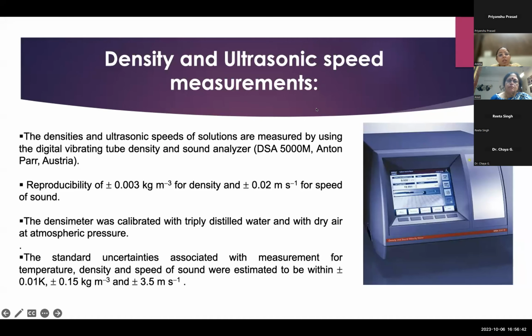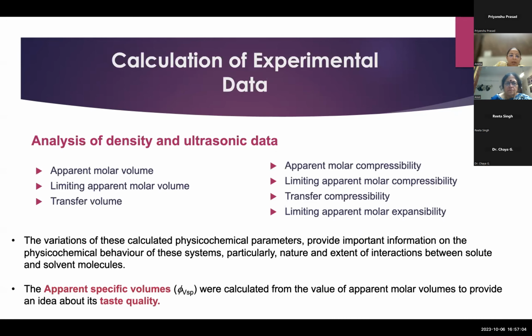Then the density and ultrasonic speed measurements were done using the DSA 5000M, that is, a digital vibrating tube density and sound analyzer. Through this instrument, both of these quantities were measured with great reproducibility and low uncertainty. From these values, various derived parameters were calculated, like apparent molar volume, limiting apparent molar volume, transfer volume, and the compressibilities in the same ranges.